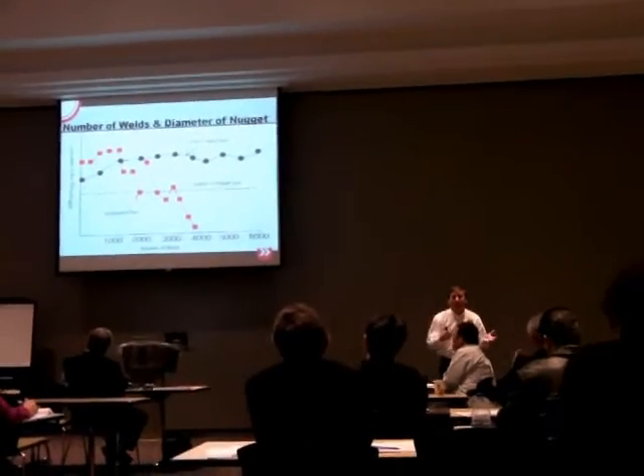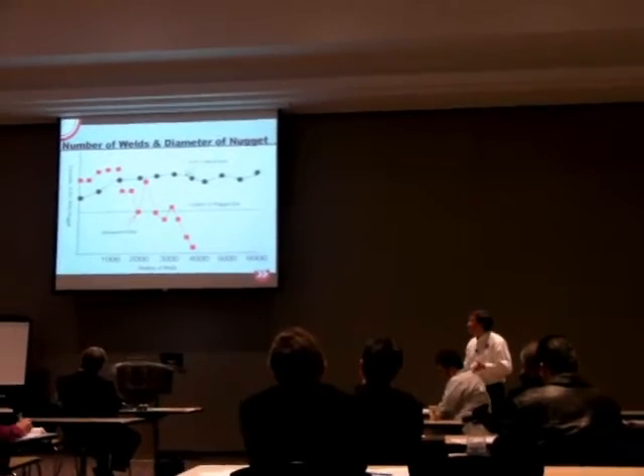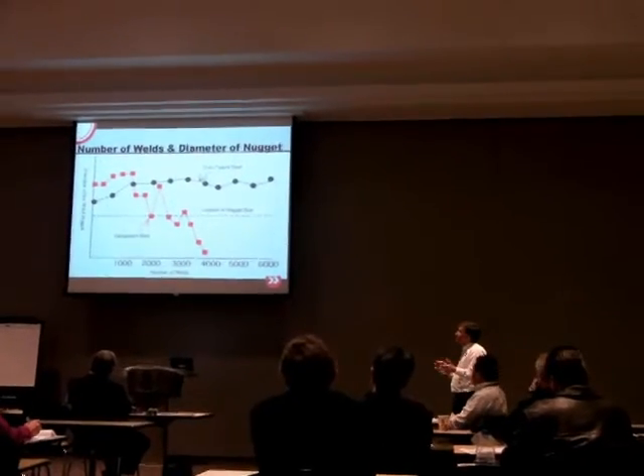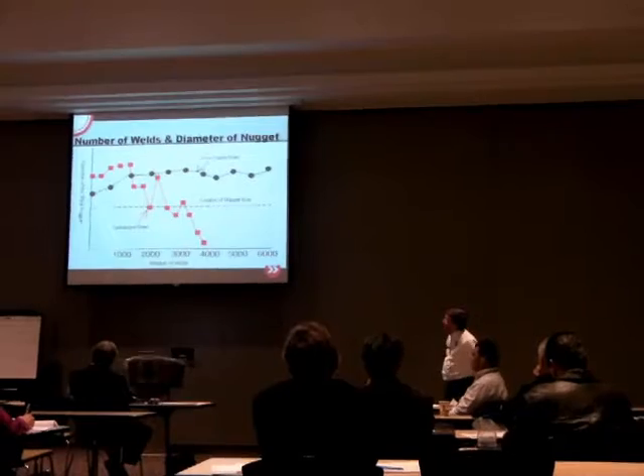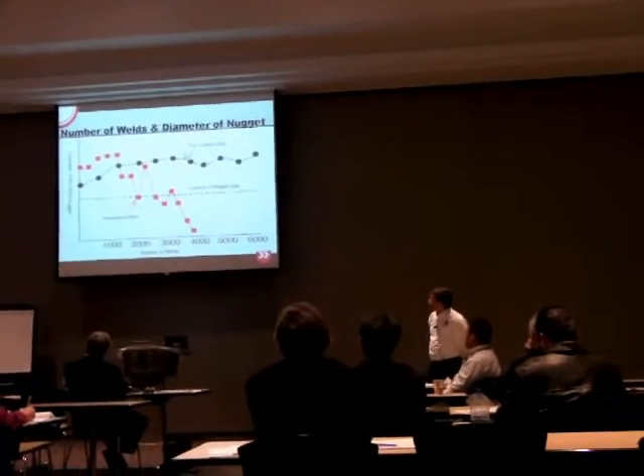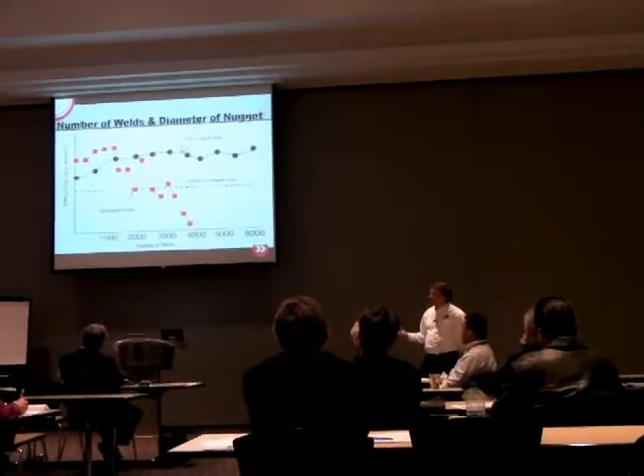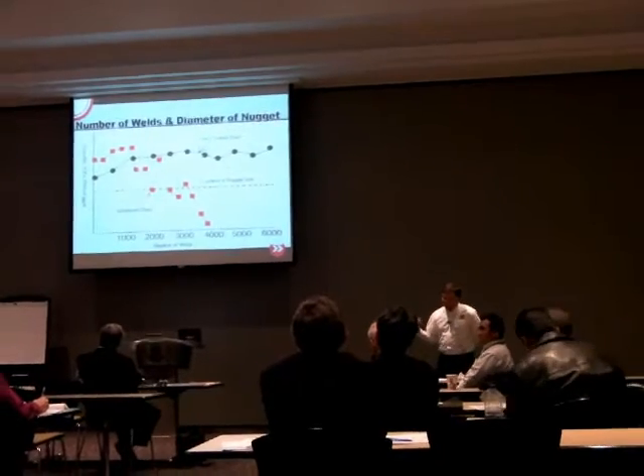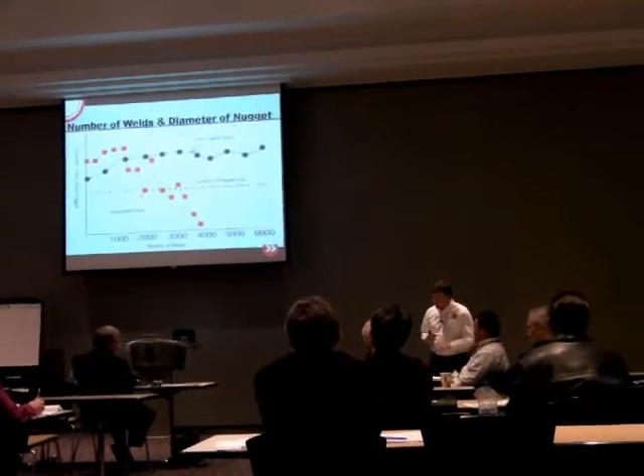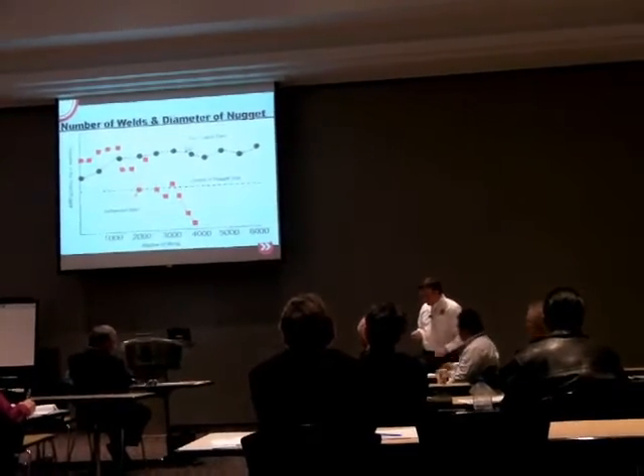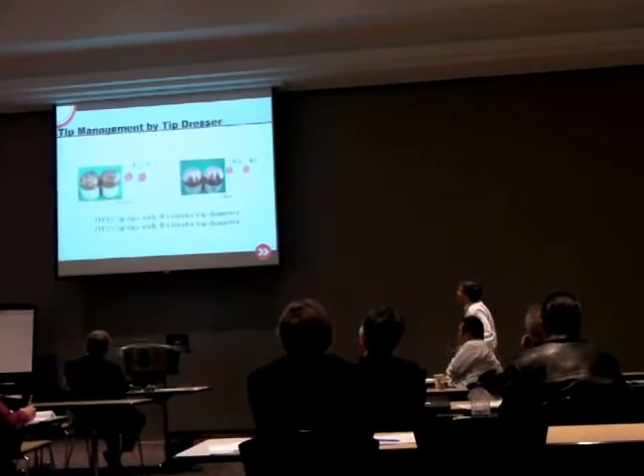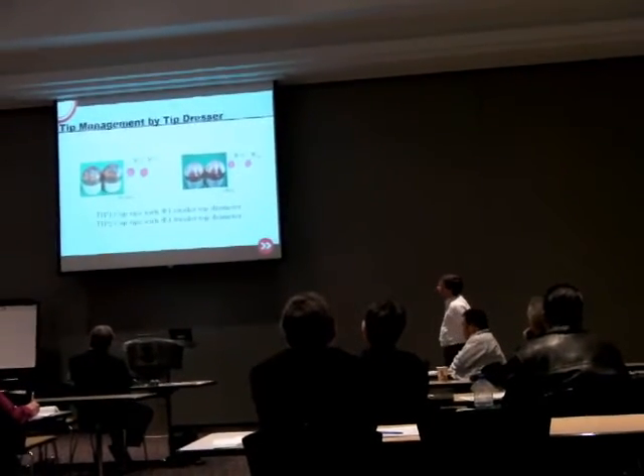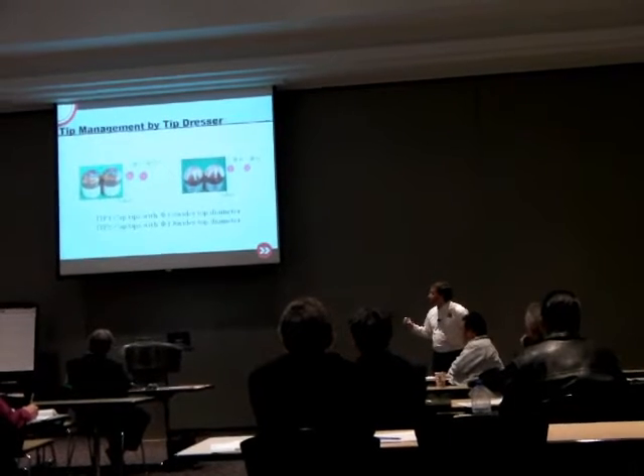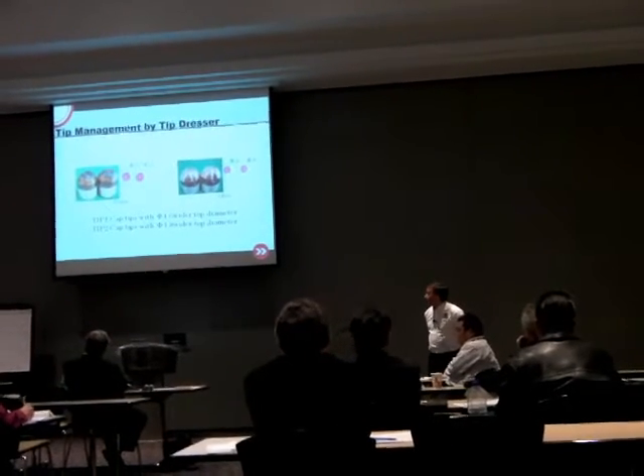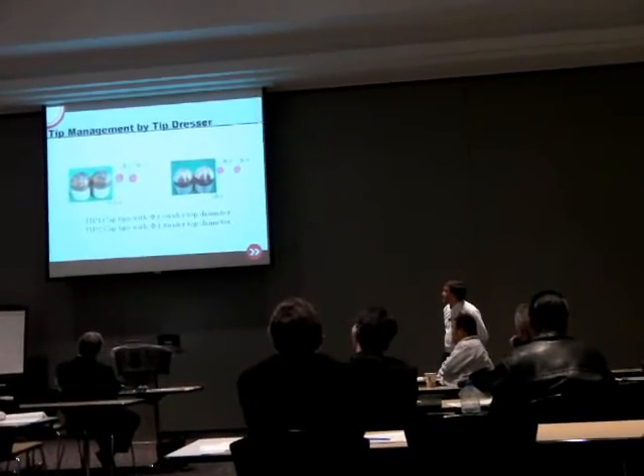Anytime we have a problem, if it's consistent, we can usually find a solution. But when we're dealing with galvanized material, you see how inconsistent that is, and that's where we have to have a solution. And we feel like the solution is by using tip dressing. Here we're going to talk about tip management by tip dressing. Like I said, we feel like this is the solution to be able to keep a clean cap face and keep your resistance the same throughout.